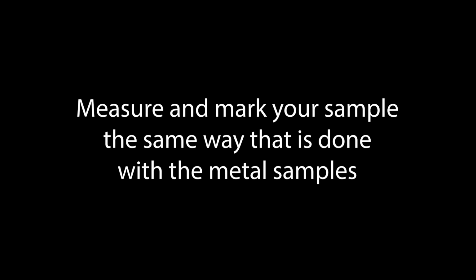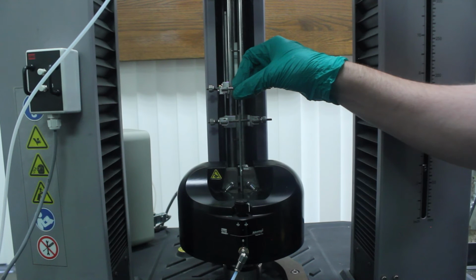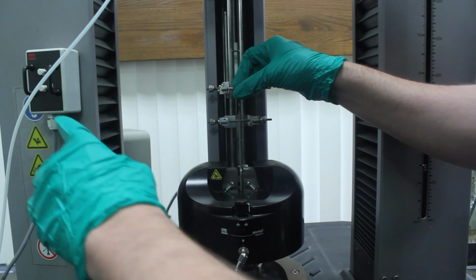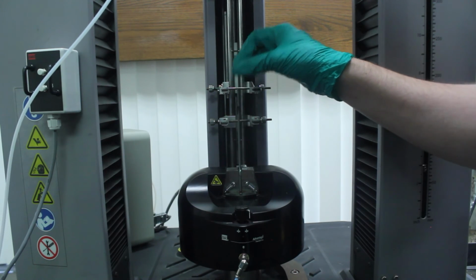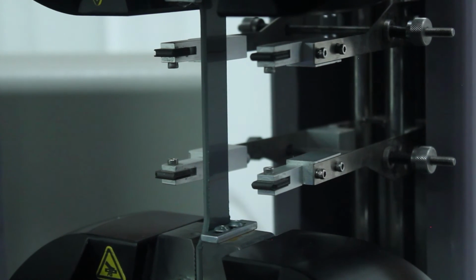Before inserting your sample, make sure to measure and mark it the same way you did for the metal ones. Just as you did with your metal tensile sample, insert it into the lower grip head and then make sure the shoulders are below the edge of the grip head and then press the A button to clamp it down.